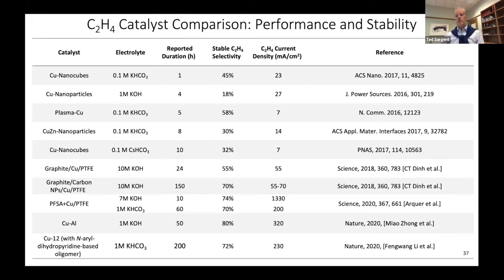So summarizing where we got on the reductive side at this point in the project, I'll just say that for the past, say, 5 years or so, there had been reports, typically measured in the hours, of CO2 reduction to ethylene. Faradaic efficiencies were in the 30 to 60% range. And because people were working in H cells, the mass transport limits of CO2 in water were limiting them to the tens of milliamps, as shown in this column.